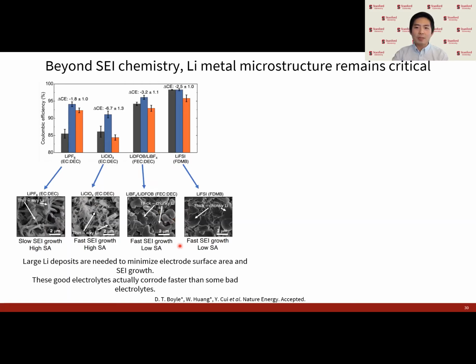And these large lithium deposits reduce the lithium surface area, but at the same time, what we see in these coulometry measurements is that the amount of capacity loss is similar or worse than some of these high surface area chemistries such as PF6 or perchlorate. And it tells us that these electrolyte systems, even though they have much lower surface area, are actually more reactive than this PF6 in carbonate, for example.